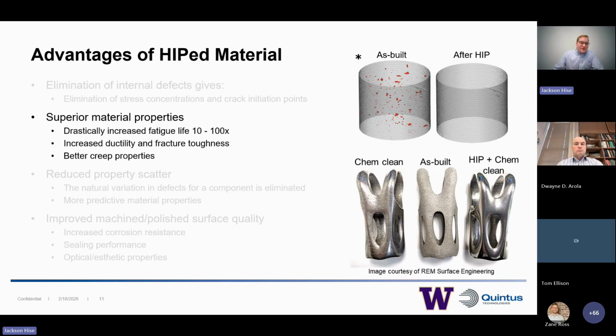So I spoke to the elimination of internal defects, but this really produces superior material properties. We see that HIPped materials have dramatically increased fatigue life, up to 100 times, increased ductility and fracture toughness, and better creep properties. If we're thinking of something like GRX-810, a recent ODS alloy that came out of NASA, we see that the HIPped version has a creep value 2 times as large as the printed use case.